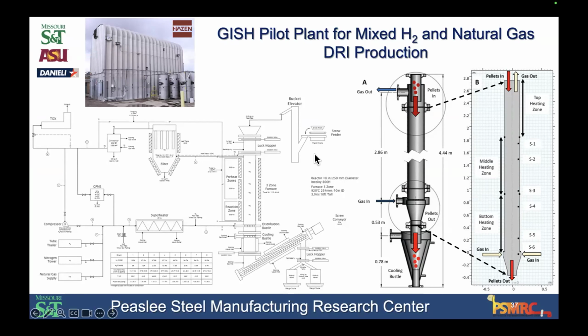It is a countercurrent reactor where pellets are fed in at the top through an interlock system. Preheated gases are fed in the bottom. The gases go up and then exit the system. The pellets go downward and then exit the system. These pellets are entirely sealed so that they can be packaged in drums without any exposure to air. The off-gas system goes through a condenser to take the water out of the system, and the hydrogen that is remaining then recycles back into the reactor. So it's a fairly complex reactor. It was designed to produce well in excess of 1 ton a week of material, which allowed us to get enough material to do bulk melting trials in commercial environments.